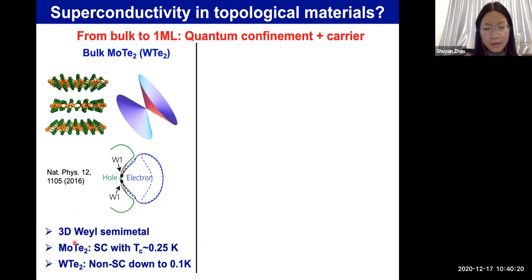Now for the related material, tungsten ditelluride, superconductivity occurs at an even lower temperature. It's not superconducting even down to 0.1 Kelvin.